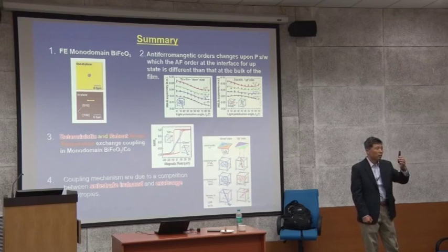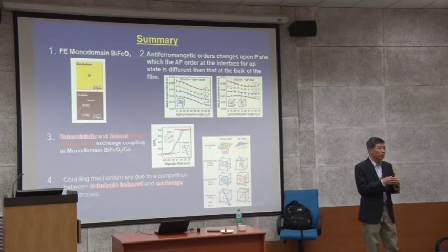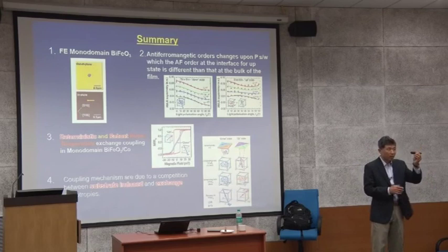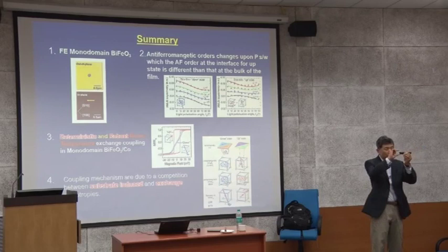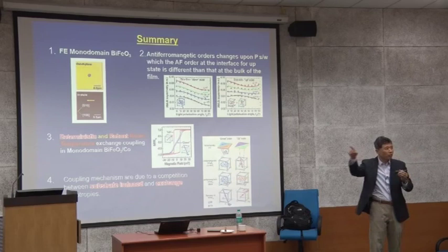So it depends on thickness, and then on how your domain structure grows. With a very thick film, you more likely end up with a messy domain structure. A very thin one is only up and down. And those things can easily be seen with just X-ray. You don't even have to go to PFM, because you have this way and that way. The lattice parameter of this one is long, and of this one is short. That means with a simple X-ray theta-2theta scan, you can use the peak splitting.